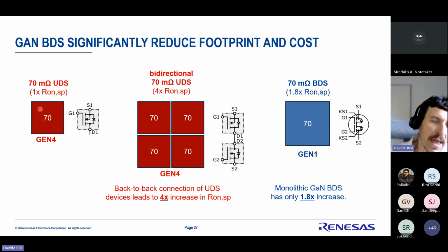Let's take here a single device, let's call it a 70 milliohm unidirectional device, and it has 1 times the specific Ron. So it has a certain chip size. This is Gen 4, the Transphorm Gen 4. If you want now to make a back-to-back connection using unidirectional devices and still keep a total resistance of 70 milliohm, you see that now you need 4 times the area, because now you have 70 back-to-back, that becomes 140, and then you need to have 2 more in parallel to go back to 70.